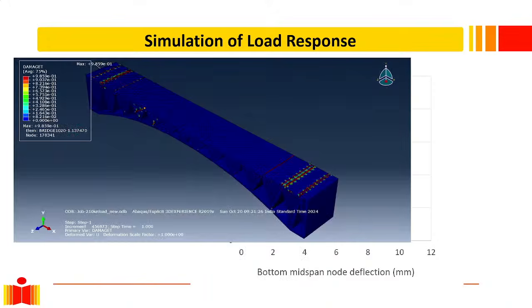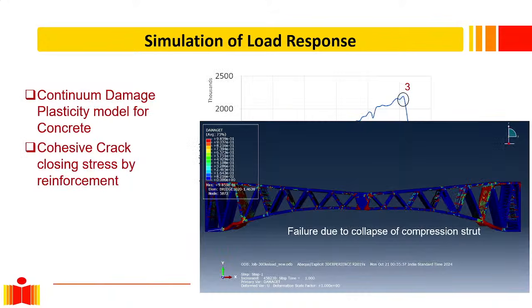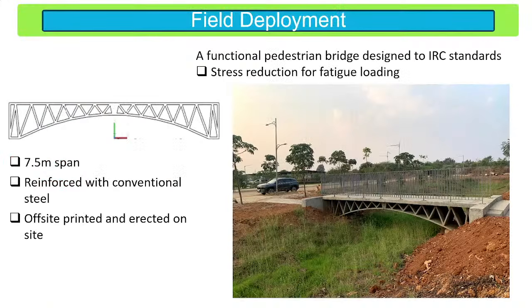Just to show you the sequence of damage, here is the tensile cracking at different points in the load response. And the final failure is because of compression damage in the strut. This is the final bridge that was installed. It is offsite printed, 2 segments with a closure pour. This bridge has been designed as per standards as a pedestrian bridge, but of course our load analysis reveals that we could actually carry significant traffic loading if we had to.